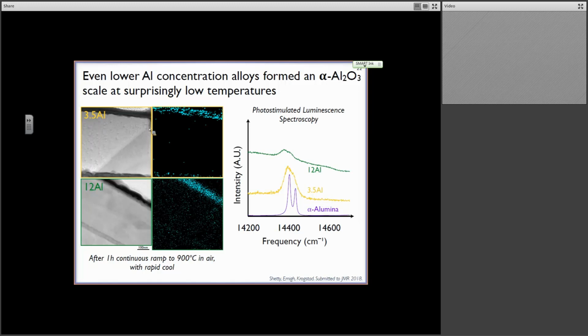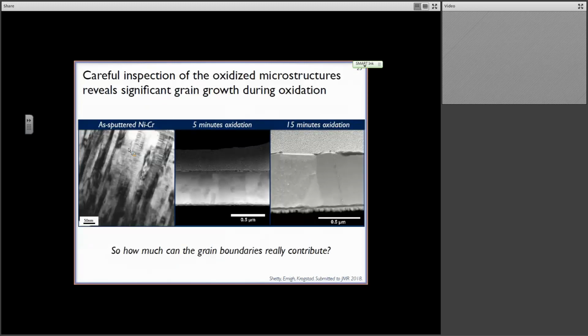The contrast that you're seeing here, this line, is the only grain boundary that you can see in this field of view, because the microstructure has coarsened so rapidly over this 1 hour at 900 degrees C that it has effectively become a bamboo-like structure, where the size of the grains is the full thickness of the film. And so these are now micron-sized grains. They're not nanocrystalline anymore. So if they're not nanocrystalline, then how much is this whole nanocrystalline idea really impacting the oxidation behavior? And here's a little bit closer inspection.